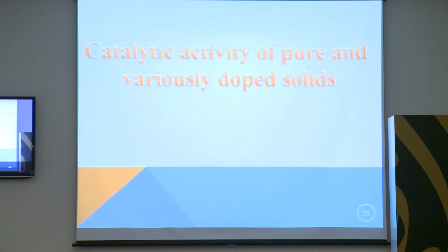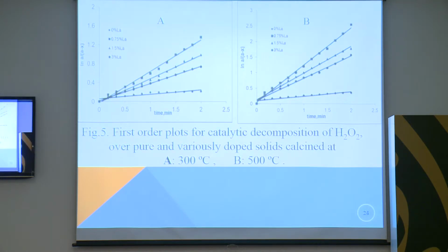In studying the catalytic activity of pure and variously doped solids, the first order plot of catalytic decomposition of our pure and variously doped solids calcined at 300 and 500 shows that the sample doped with 0.75 mole percent lanthanum oxide was the most catalytically active, which may be due to increasing the concentration of manganese species on the surface and decreasing the crystal size. But further increase in the dopant percentage led to a decrease in the catalytic activity, which may be due to decreasing the percentage of manganese species on the surface. Increasing the calcination temperature to 500, as in figure B, led to increasing the catalytic reaction activity, which may be due to increasing the surface area, as obtained in the surface characteristics.